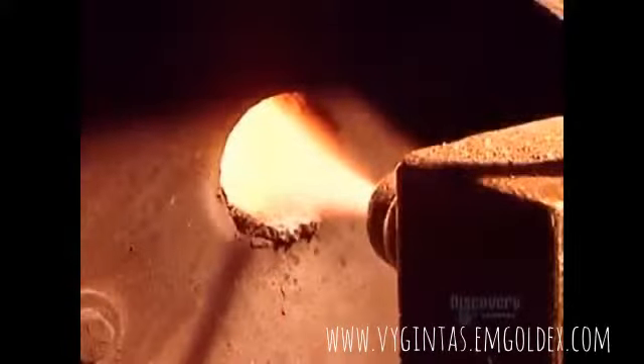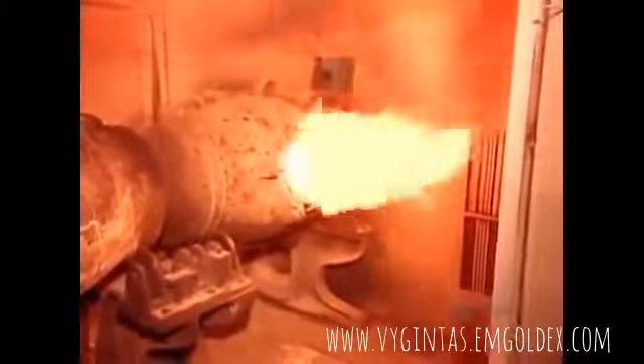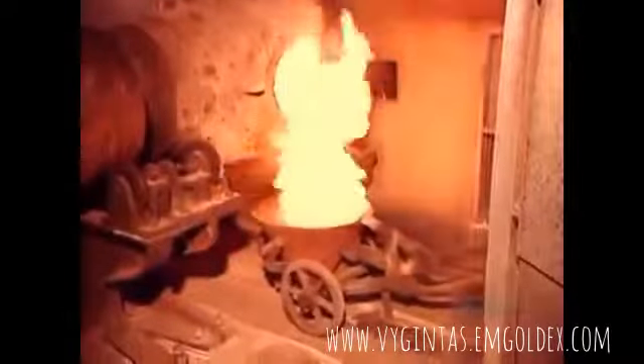They pour it into the smelter, whose temperature is a fiery 1600 degrees Celsius. They rotate the smelter so that the contents heat evenly. Over 2.5 hours, the heavier gold eventually sinks to the bottom, while the impurities, called slag, float to the surface.